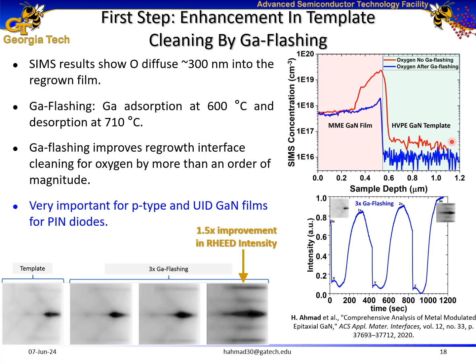From one of my SIMS studies, I found that there is a high level of oxygen diffusing from the regrowth interface into the films. So I used a method of gallium flashing, which is adsorption of gallium at a lower substrate temperature and desorption at a higher substrate temperature. By using this technique, I saw improvement both from RHEED intensity transients and also from SIMS. I was able to achieve an improvement of more than 1 order of magnitude in regrowth interface cleaning. This is significant both for p-type gallium nitride films and also for unintentionally doped gallium nitride films for pin diodes.